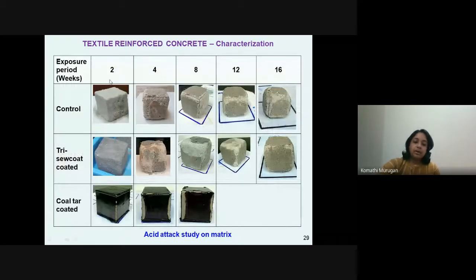So what we found on exposing these cube specimens in acids, on exposure to certain periods such as 4, 8, 12, 16, and now we are into 20, 24 weeks, is that there is a certain mass loss and dimension change that is observed in these systems. So what we are looking at is the development of the service life models and the prediction of the lifetime for over 50 years, what happens, over 100 years, what happens. So essentially this study looks at the development of the service life models for prediction of the service life of these systems. So what I've shown is a matrix here.